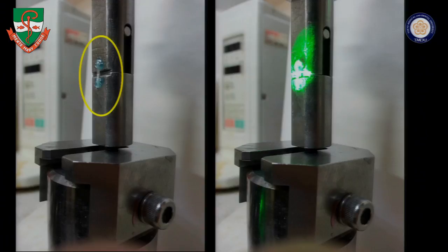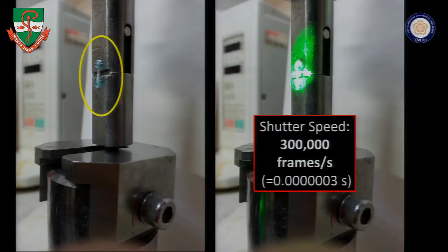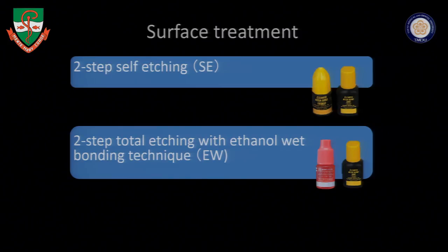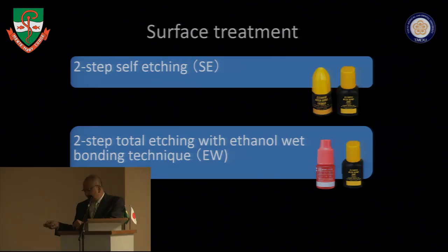But it's not so easy to observe it. We utilize the laser pulse. The number of the pulse was 300,000 per second. That's why we could observe the fracture with the very high-speed recording, 300,000 frames per second. It's an amazing number. And we prepared two kinds of specimens, that is two-step self-etching and two-step total etching with ethanol wet bonding technique, that is ethanol wet bonding technique.